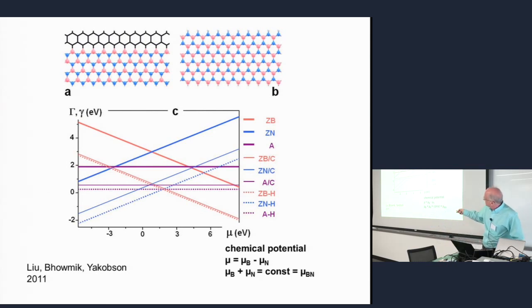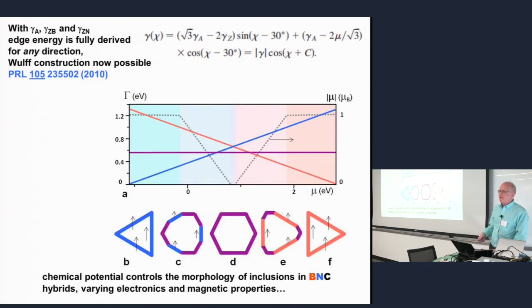So that's what this plot shows. And I don't go through details. But you see, if it's boron rich, and this is boron chemical potential, then it goes down. And if it's nitrogen rich in this case, then it goes up. And accordingly, if you want to know the thermodynamic shape of a crystal, of course, you have to use the Wulff construction. That's where edge energy goes in. You get different results. So for BN even, it's quite fascinating.